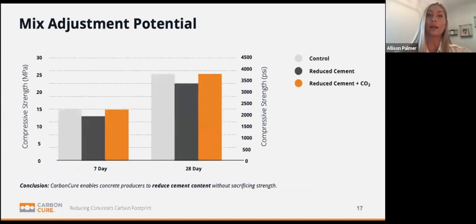Higher strength allows us to optimize our mix designs and reduce our cement content. So this is where the real value of the CarbonCure technology comes in, especially in relation to carbon savings. What we're looking at here is an example of a case study of a concrete mix that normally reaches about 4,000 PSI at 28 days.